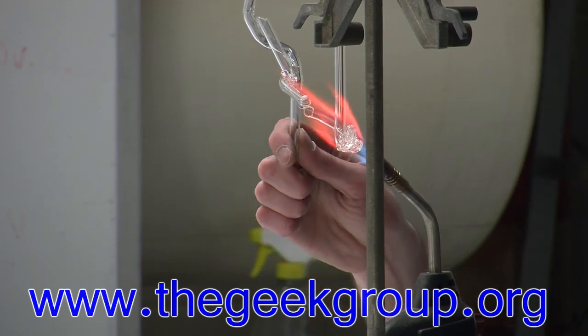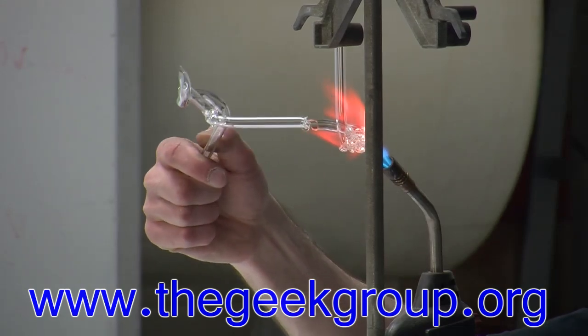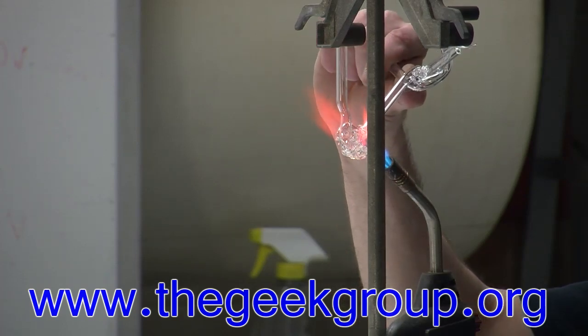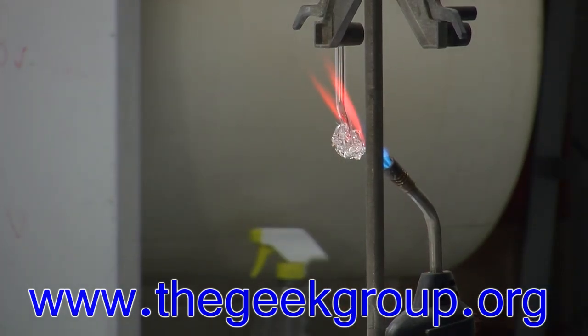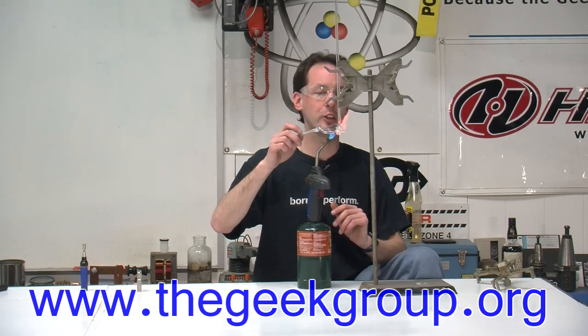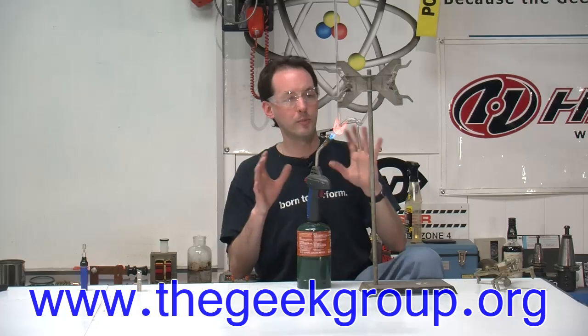I'm just gonna poke this in and try and wad it all up. You can do this with metal tools, like I could use my Gerber to push this around, but two things happen. One, the Gerber gets really hot and uncomfortable to hold. And two, as the Gerber draws heat energy away, it creates cold spots and it'll crack. You really gotta focus on even heating when you're playing with glass, because if you have cold spots, it'll mess up. So now I've got a whole bunch of weight there.